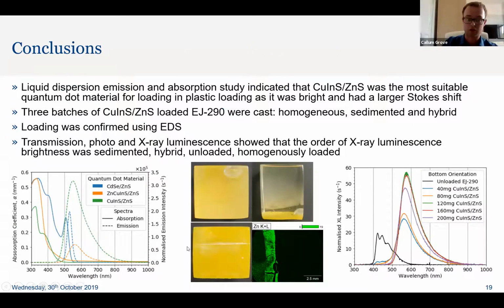So overall, we came to the conclusion that the sedimented loaded plastic scintillators are potentially the best way to go. So the next step will be to try and get a large enough and highly loaded enough scintillator to get an energy resolution out, or potentially just use a thin quantum dot region rather than having the plastic substrate attached to the other side. So sorry for going over, and thank you for listening.